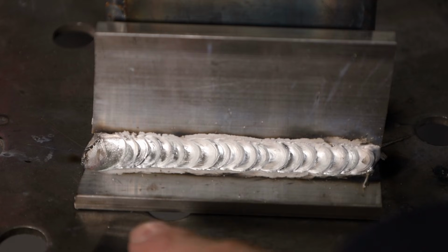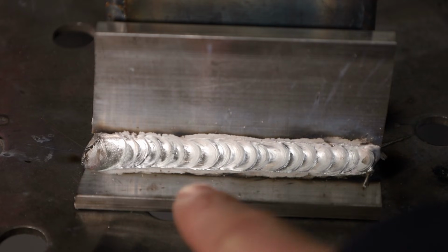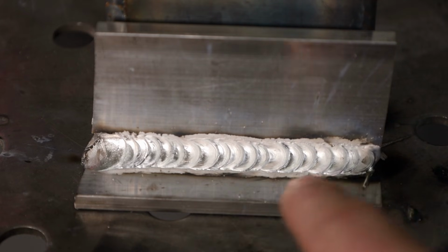But you can see it's running pretty well here, actually. Just trying to preheat to about 200 degrees, not too hot there, to be able to affect the microstructure of the metal. But anyway, take a look at that result. That is not bad for welding on quarter inch thick plate with this spool gun machine. So I'll run the other side while it's set up, you know, might as well, it's there. And once again, it's running pretty good.